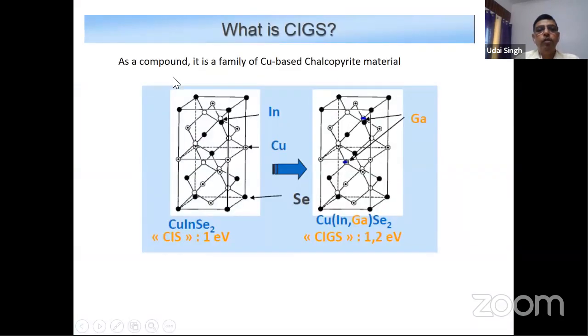You see the crystal structure is basically a copper-based chalcopyrite material. So copper, indium, and selenide. Now, if you replace some of the indium by gallium, you get copper indium gallium selenide. This is 1 electron volt, but you can go more than 1 electron volt. You can also replace selenium by sulfur, so you can increase the band gap. But other problems come in there. The best efficiency was achieved for around 1.2 electron volt.